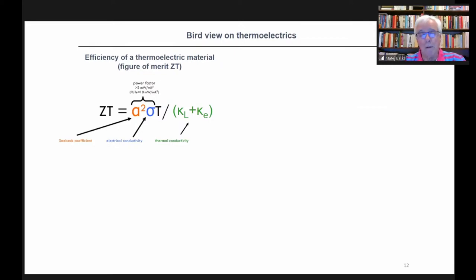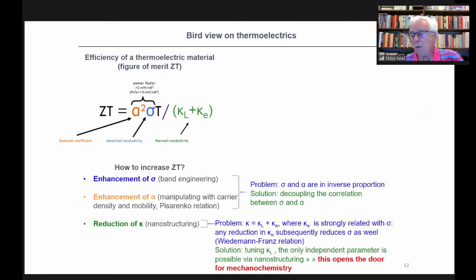Well, this is not so simple, because the laws of physics conspire against satisfying this requirement. First is the so-called Wiedemann-Franz law, which says that there is a relation under which the electronic thermal conductivity is proportional to electrical conductivity. So if you increase this parameter, the second one will also increase. So they are going against each other.